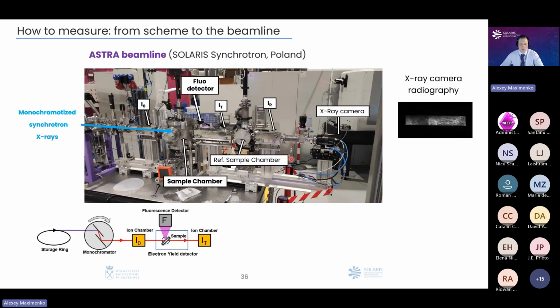And in principle, in most of the cases, no matter where it is the beamline, absorption spectroscopy beamline at Solaris or at SRF, ALBA, most of the beamlines have the same constructions, that you have a detector which allows you to detect the incident monochromatic radiation before your sample, the detector which allows you to detect the radiation after your sample. Also, you have here a fluorescence detector. And also you have an equipment which allows you to measure the current which appears on your sample. Sometimes you also could have a reference sample. It means that you measure your main sample and the reference sample simultaneously in order to be very sure and very precise what is the position of this absorption edge of your sample which you are measuring. Also, sometimes you also have a X-ray camera which allows you to see on which place of the sample you are hitting, and for example to choose a proper place on your sample.